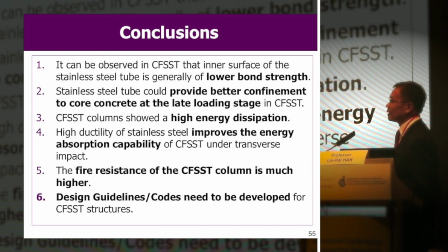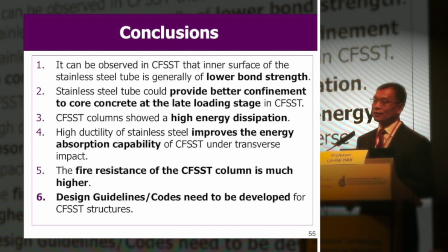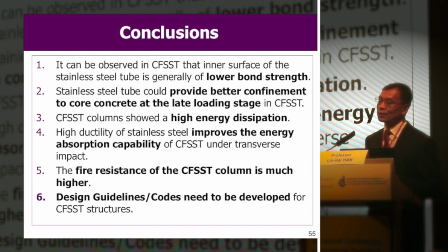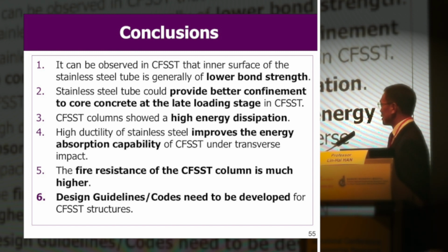Actually, stainless steel tube can provide better confinement, particularly at the later stage because of strain hardening of the material. The CFSST column has higher energy dissipation and also higher energy absorption ability under cyclic loading and impact loading. The fire resistance of the CFSST is much higher than that of the corresponding carbon steel tube filled with concrete. So in most cases in practice, without any additional fire protection, the concrete filled stainless steel tubular column can achieve more than 3 hours of fire resistance. This is good news for this type of structures.